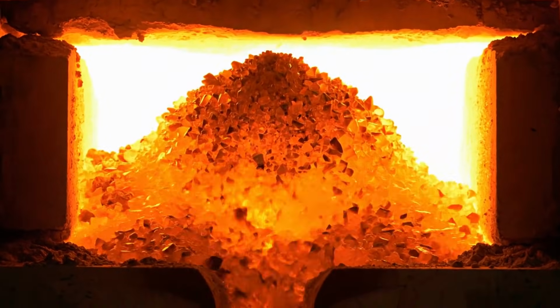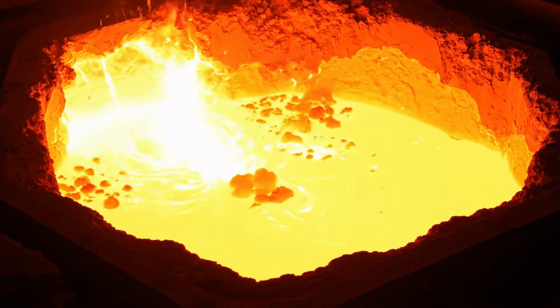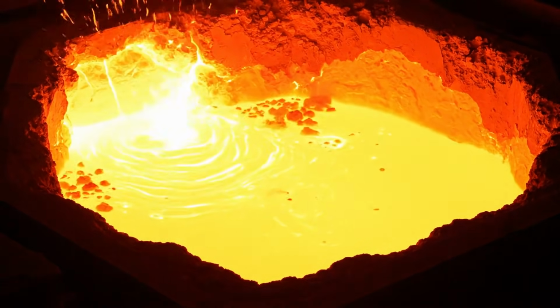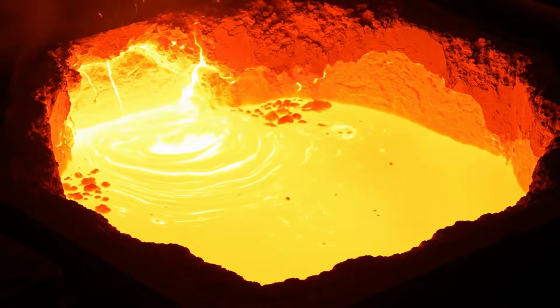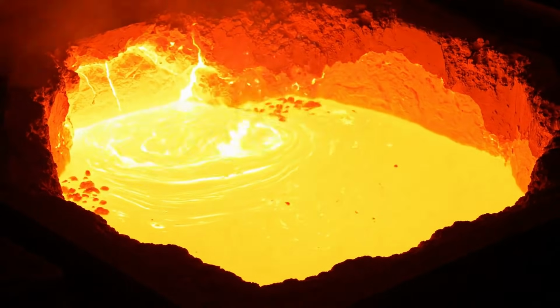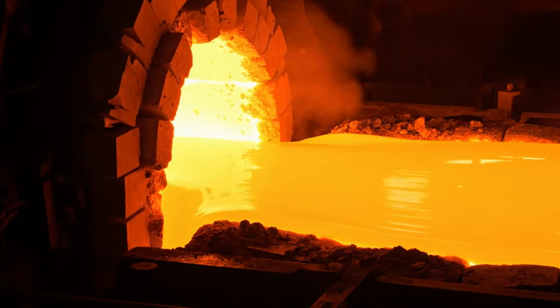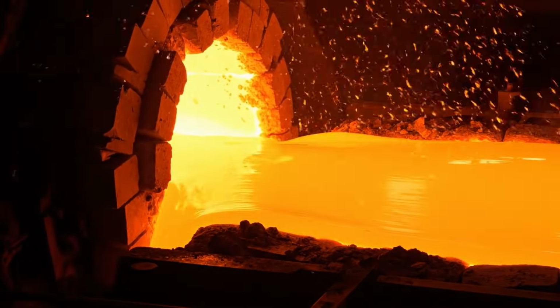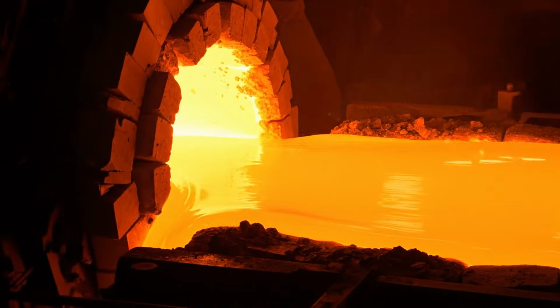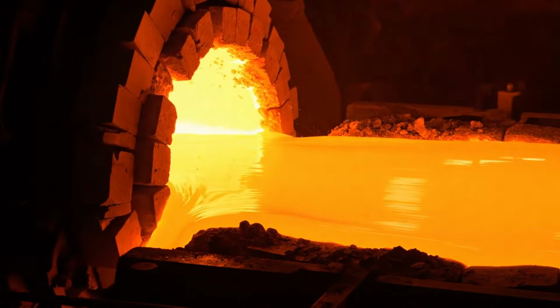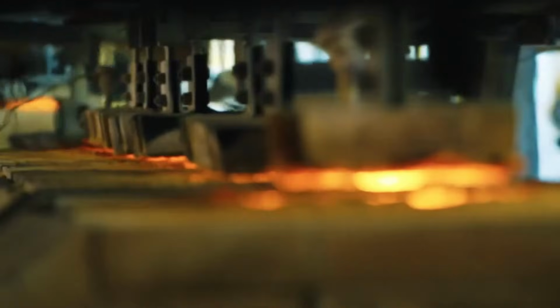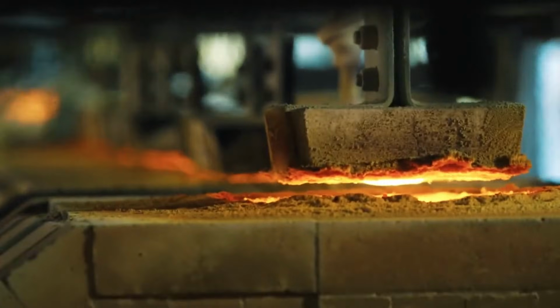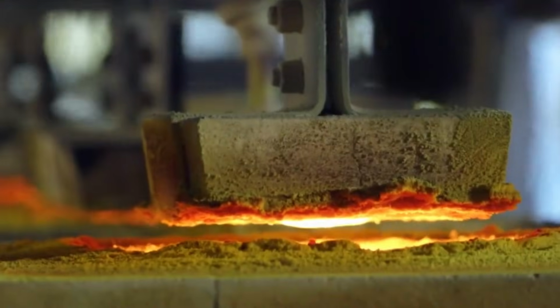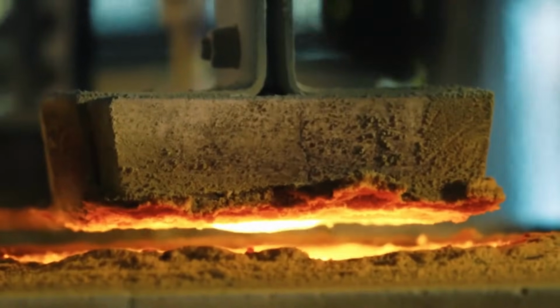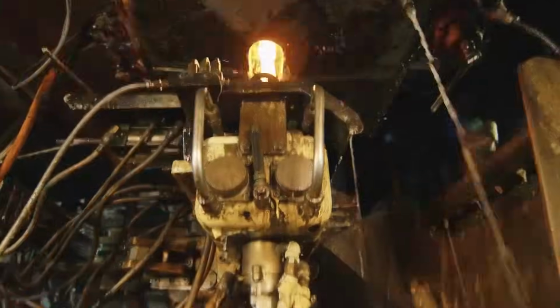Over approximately 24 hours, the solid ingredients gradually liquefy into molten glass, a dense, glowing mass with the consistency of thick honey. For the next several hours, the molten glass remains at temperature, allowing trapped gases to escape. This fining process ensures the highest purity and clarity in the final product. Tiny bubbles of carbon dioxide from limestone decomposition and other gases naturally migrate to the surface and dissipate, leaving crystal clear molten glass.